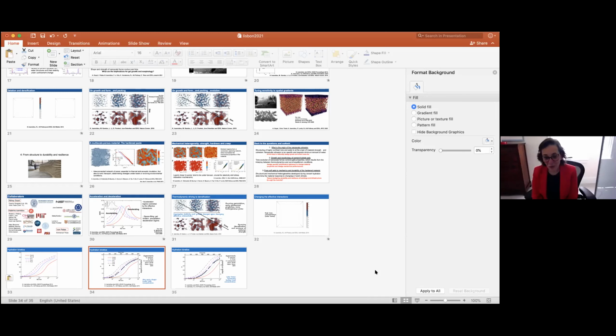In fact, I have to confess that we don't do it. What I showed you is this first study where we fix one type of interaction, and then we watch the relaxation with that type of interaction fixed. So we don't change it. We did that because we wanted to understand, if I have just one type of interaction, which type of gel would I get, changing the gelation rate. Once you understand that, and you get this picture, okay, so the time evolution must be important, then you would like to go back and do exactly what you said, to actually be able to mimic a process in which this evolves over time.